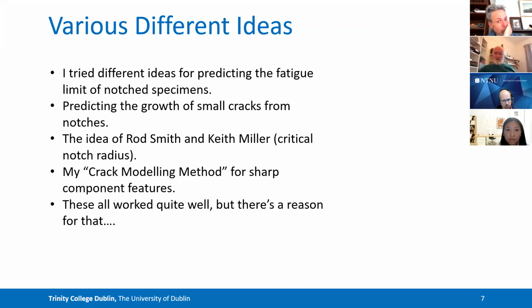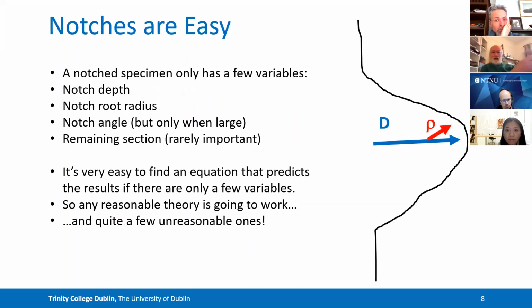And this all worked quite well. But there is a reason why notches are easy. I say that because if your problem is to predict fatigue from a notched specimen, very crudely drawn there by me on the right, the notched specimen only has a few parameters in it. It's got a depth, it's got a root radius, and those are the two main ones. It also has an opening angle, but that only really affects the stresses if the angle is quite large. And there's also a remaining section, which is rare. It is important in some cases, but not very often.